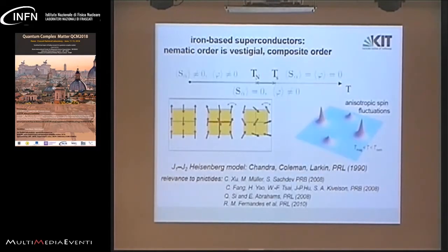I get to that. In the inelastic neutron scattering, in this intermediate regime, you would then have no magnetic order, but you have anisotropic fluctuations. So one of these Q points is sharp and has a large correlation length, and the other one is actually hardened. This was beautifully seen in Pengcheng Dai's data using inelastic neutron scattering. I think now 2 years ago or something, or even longer.